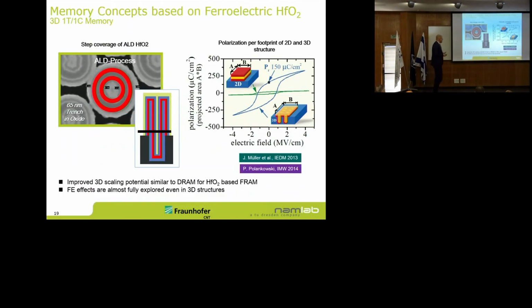If we want to integrate that into a memory, a very nice work that our colleagues from Fraunhofer CNT did, they integrated it into a device with three-dimensional capacitors. And you can see here that you actually gain the effect of the increased area, something that could never have been demonstrated with PZT or SBT. So you can see from about 10 years ago, a lot of literature from Samsung and other people that tried that, but the material on the sidewalls was never ferroelectric. With hafnium oxide, it's easy to do that, and it works immediately.